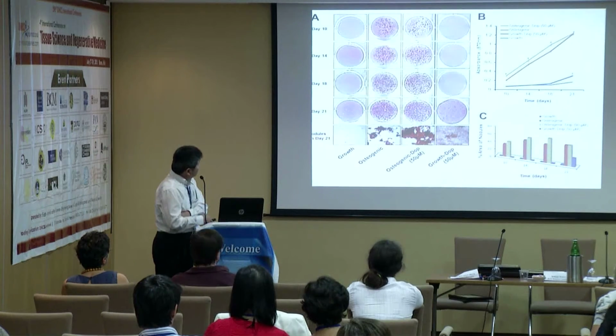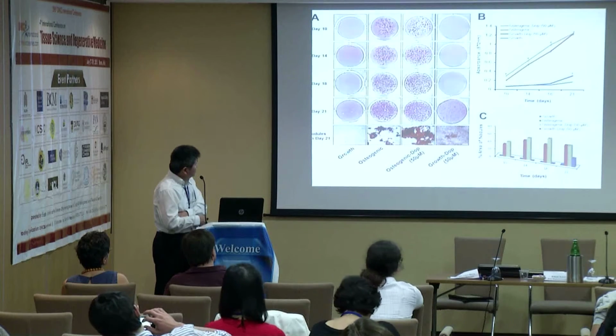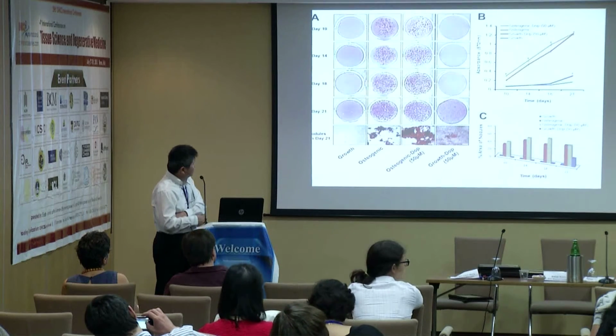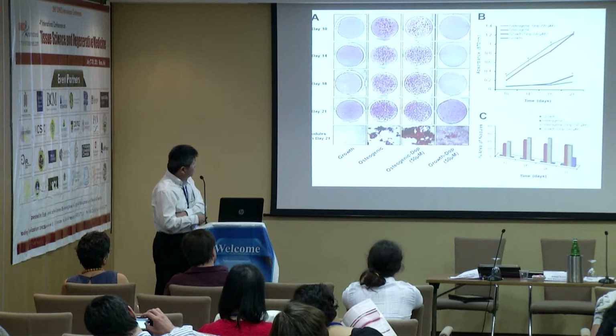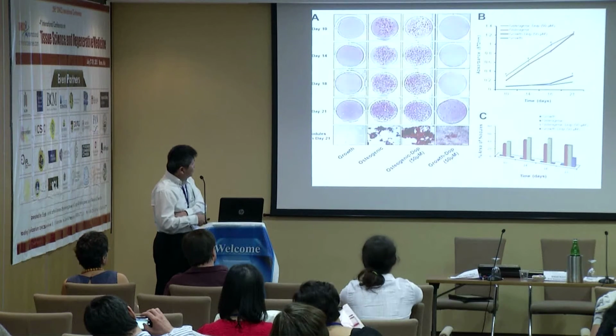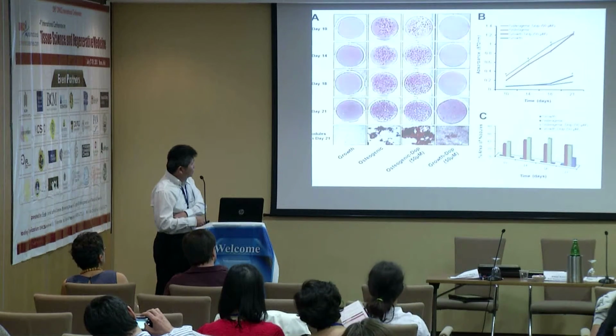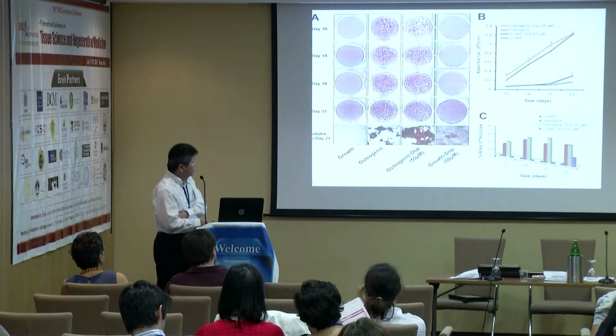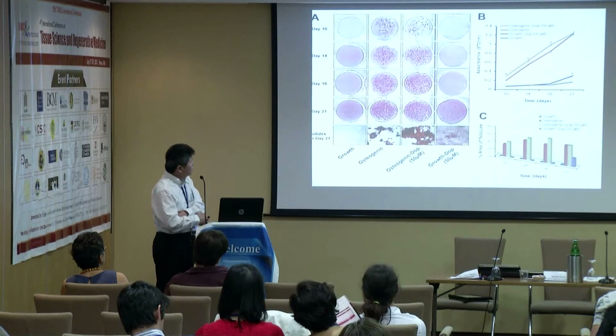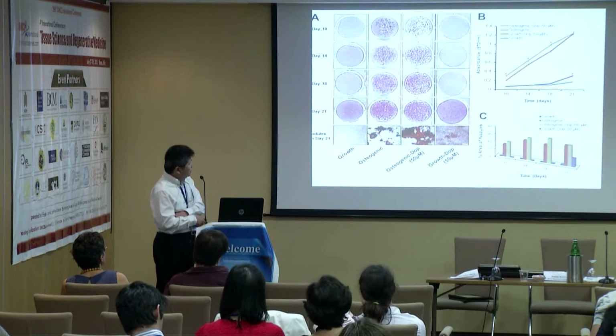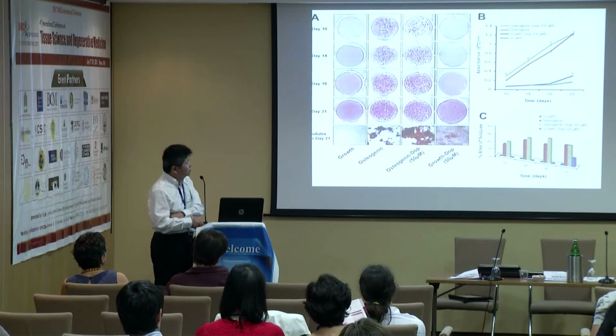And this one is showing when we put the cells under the growth medium, and compare with the growth medium plus dropping the dopamine into the culture medium at 50 micromolar, we find that just in the growth medium, it starts to form the nodule in these conditions. In the osteogenic medium, it increased just slightly, not as dramatic as in the growth medium alone.